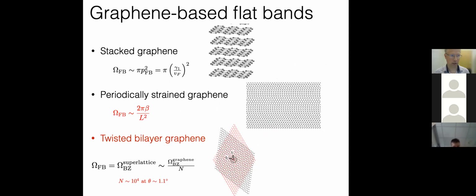I have presented to you three ways of making flat bands from graphene. They all have slightly different scaling of the size of the flat band, which also matters for the critical temperature of superconductivity. For the last one, bilayer graphene, the size of the flat band is the size of the superlattice Brillouin zone. The superlattice Brillouin zone is equal to the graphene Brillouin zone divided by the number of unit cells that go into the superlattice. As Päivi also mentioned, this n is actually 10,000 at the magic angle, which means that the size of the flat band is quite small. Nevertheless, the TC is a few Kelvin.